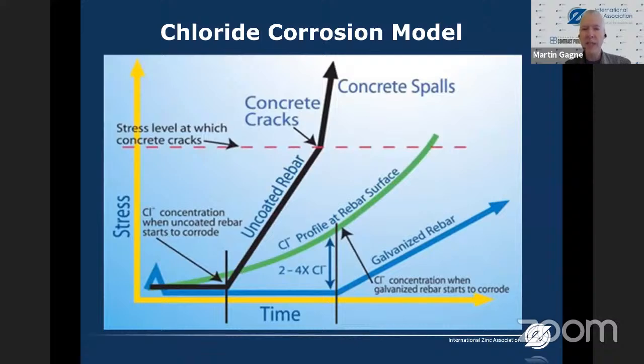Concrete is porous. The chloride ions will migrate to the rebar. When they get to the uncoated plain black reinforcing steel, there is a certain threshold amount of chloride, and when we exceed that, the black rebar will start to corrode. The corrosion products put stress on the concrete, and the concrete cracks. As was pointed out, the galvanized rebar has a much higher chloride threshold.